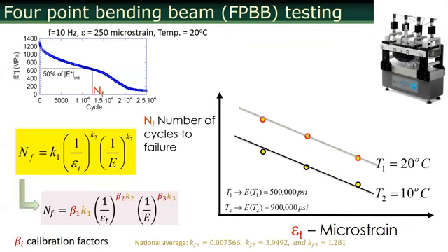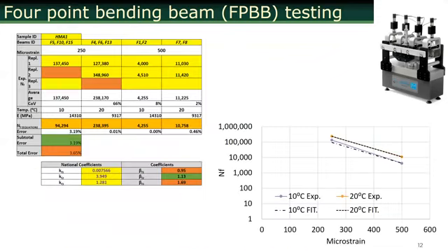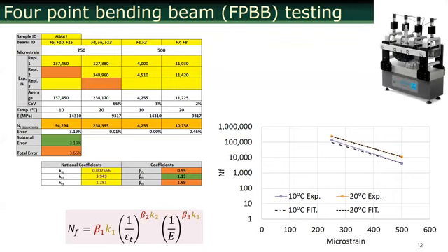So beta 1, 2, and 3 are normally 1 by default, but by just changing the beta values, you're essentially just changing the constant here. Could you just change the K value? Yeah, you can. Same thing, but it is better not to do that, so that you have a reference value and you know by multiplying beta how much deviation.